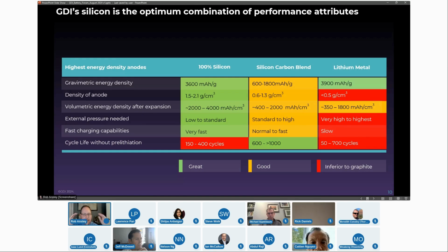So key thing that everyone needs to get in the habit of doing, stop listening to press releases, stop listening to one-liners, and start digging into the actual numbers. And the numbers that you need to know are the gravimetric energy density rating of the anode material, the density of that anode, the loading of that anode, milliamp hours per centimeter squared or milligrams per centimeter squared, and then what the volumetric energy is going to be after expansion if the material does expand, which all three of these do. So you have to figure out after expansion, what is it?